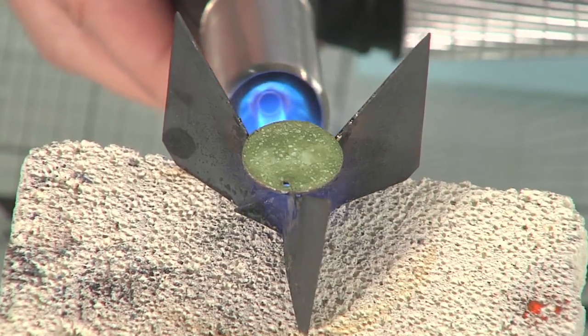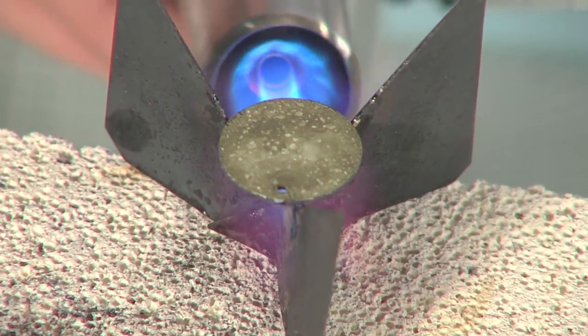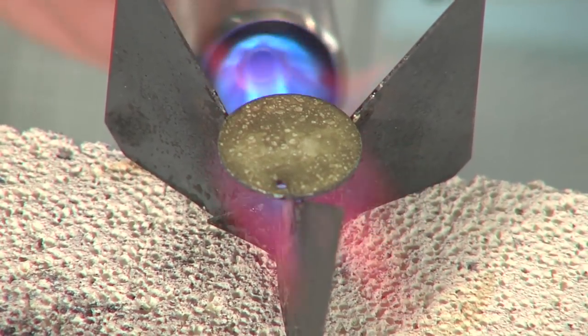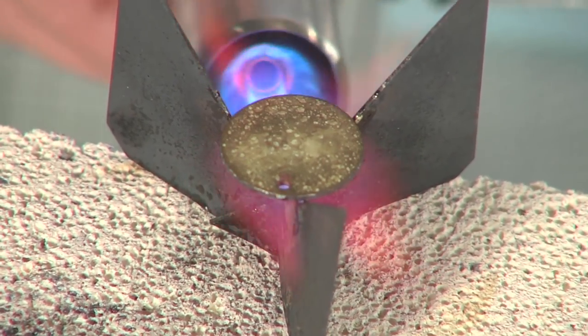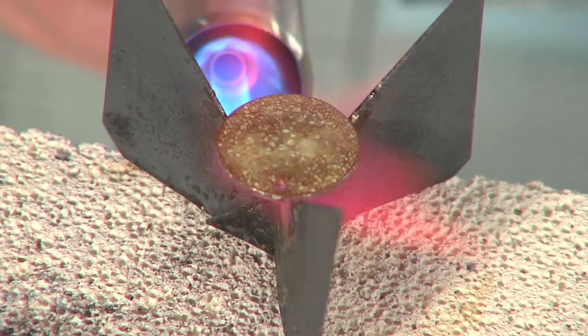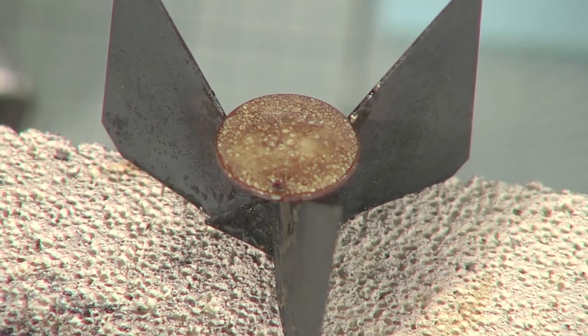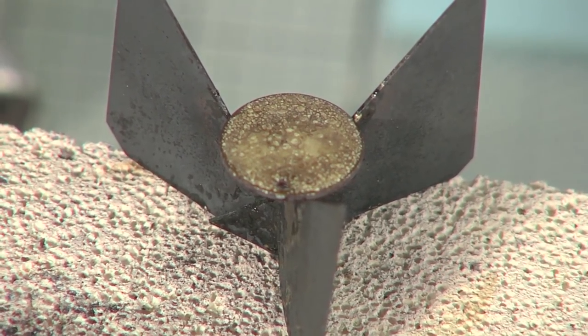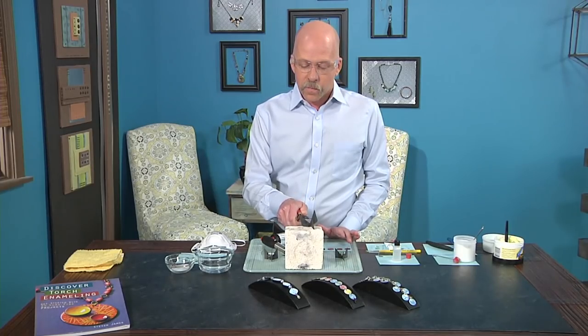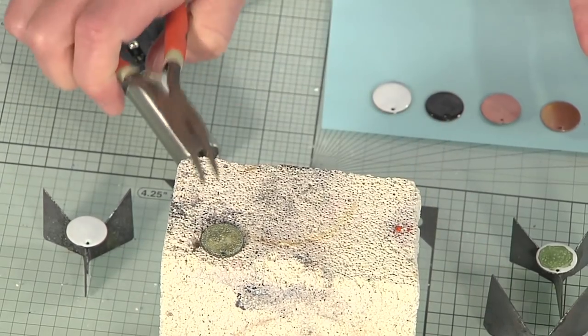At this point, you are hitting the copper piece with the tip of your flame — you want to be right in there. You can see that the enamel paint is darkening a little bit; that tells us that it's going through the stages of fusing to the color that's underneath it. It's really important to examine the piece as you're firing to make sure that you are seeing it get to that glossy stage. You can see that the enamel paint has gone from chalky to gloss. Now it is ready to be removed from the trivet. You can simply let it sit up there to cool down. I love this piece — I love that green.